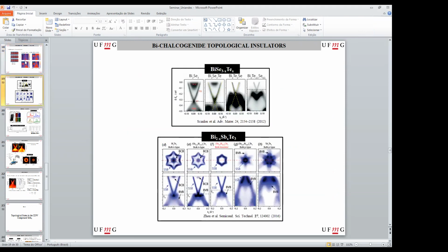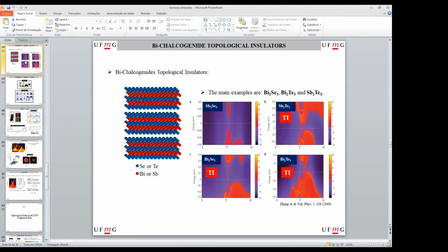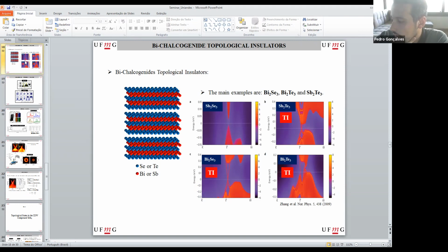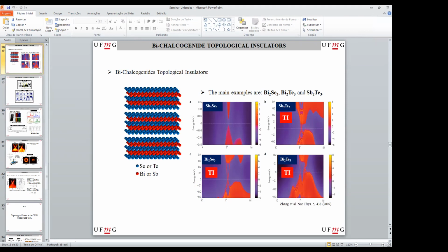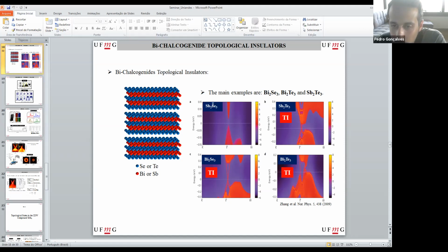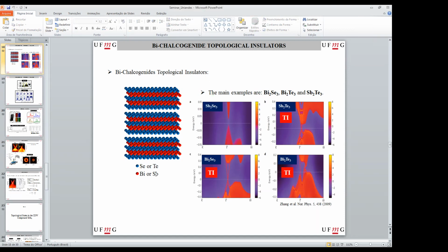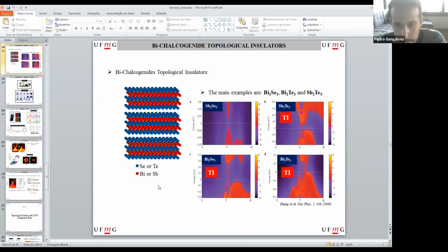Usually you have a very high spin orbit coupling, and the spin orbit coupling increases a lot. It has a very big band inversion, let's say a very robust band inversion. But actually, I think that both of them are rhomboedral, antimony selenide and bismuth telluride. I don't remember the type of structure, but the thing is, when we put antimony, the atomic structure changes. That's why the topological feature is lost.